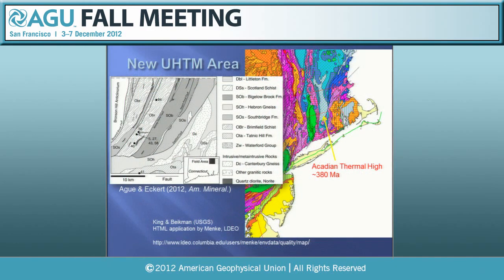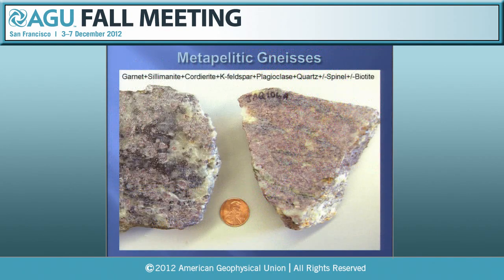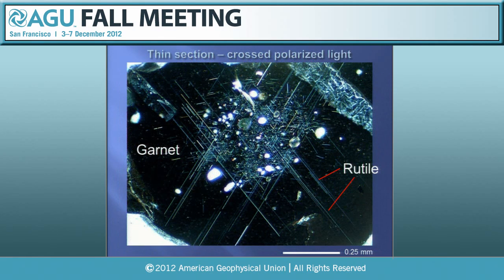I'm not going to talk about this area or other classic ones. I'm going to just introduce a new ultra-high temperature metamorphic area that we've discovered in the northeastern part of Connecticut, in the Brimfield schist. These are very high-grade rocks, and it's interesting to compare them to what's known about granulites and UHT rocks elsewhere in the world. They are, as I said, very high-grade. They contain garnet, sillimanite, cordierite, quartz, spinel, K-feldspar, large amounts of garnet, and you can see here and here. And the garnets are truly extraordinary if you look at them in thin section, because they are loaded with these crystallographically oriented needles and plates of rutile and ilmenite.